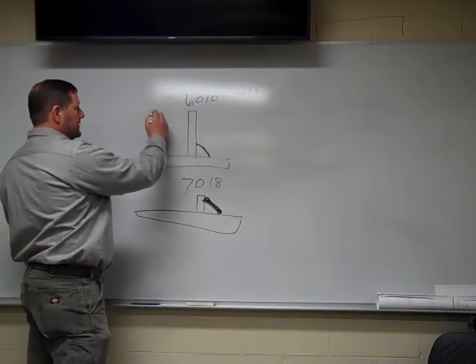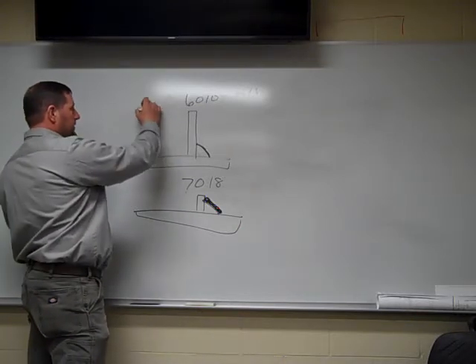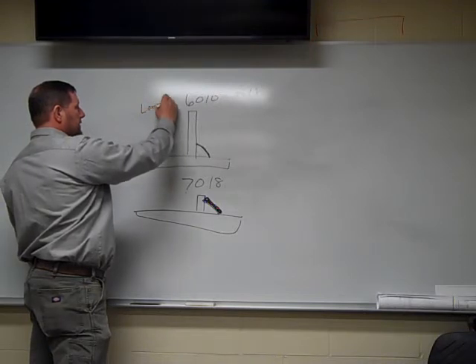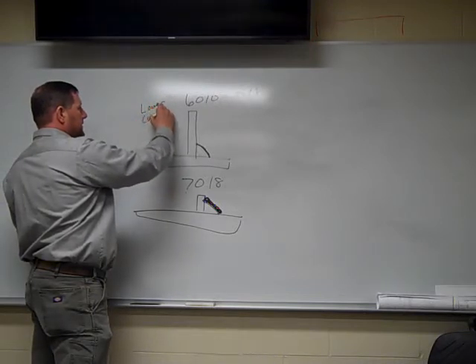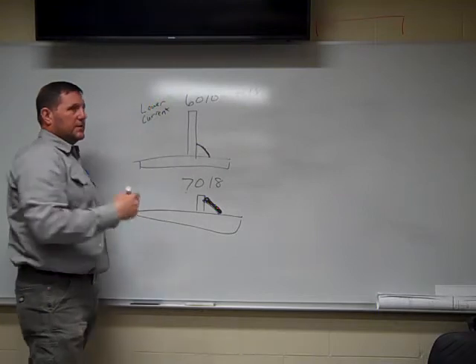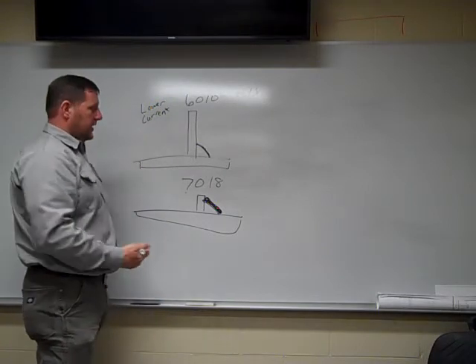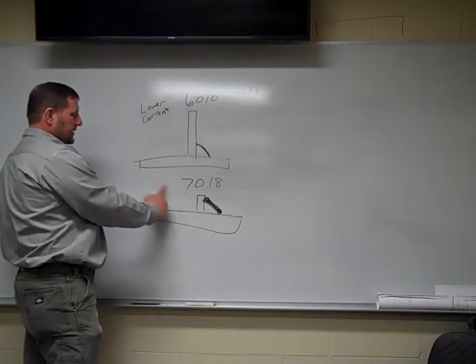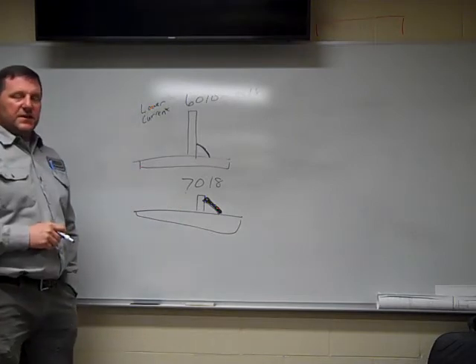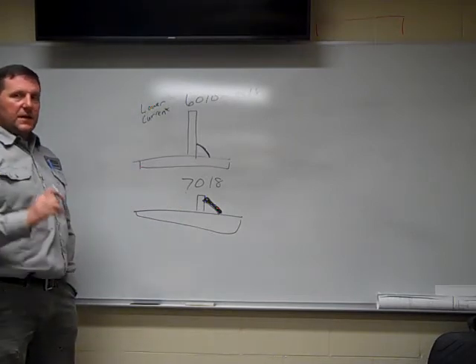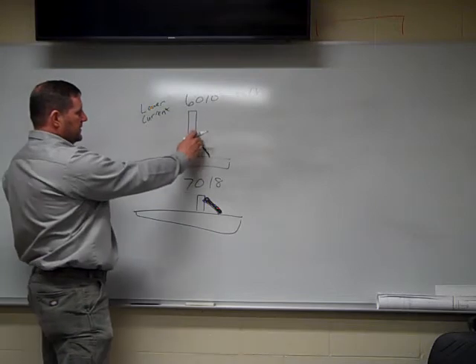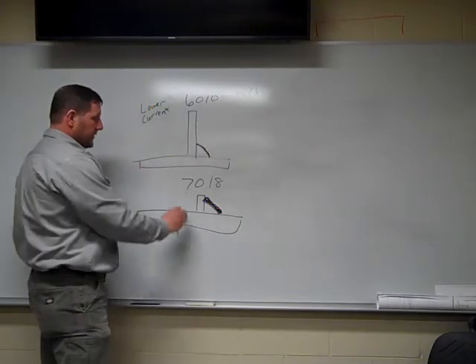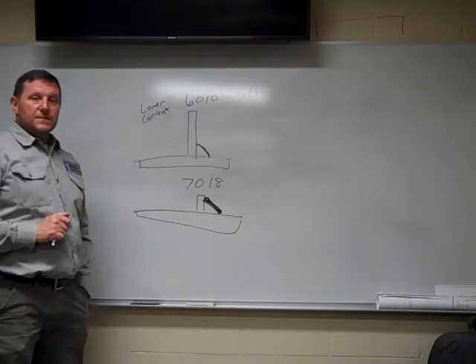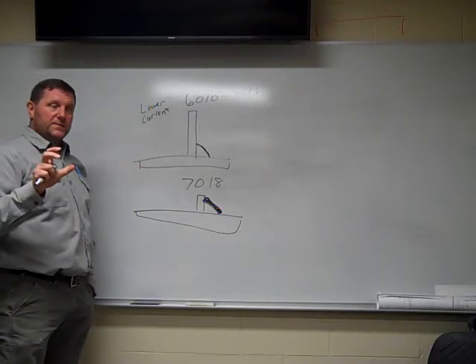You'll notice that the current settings are going to be a little bit different. You're going to have a lower current for a 6010, probably running around 90 to 100 amps, compared to your 7018, which you're probably going to run around 115 to 125 amps. And that's all because we have less flux here, we have less to melt compared to our 7018 electrode. Hopefully this was helpful.